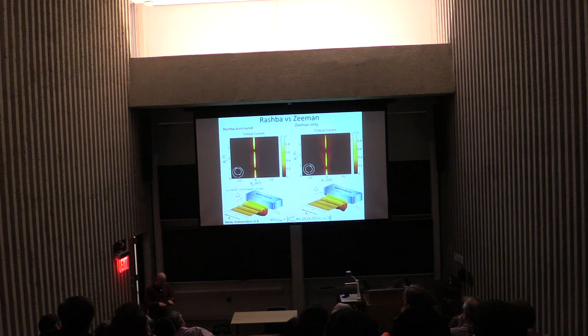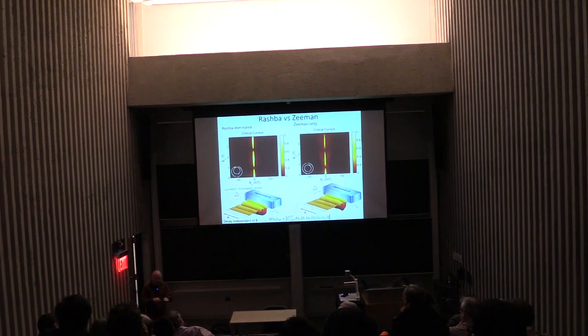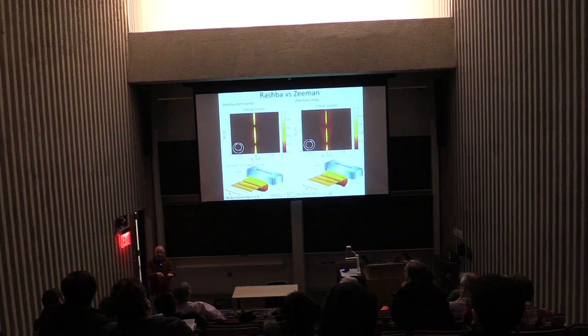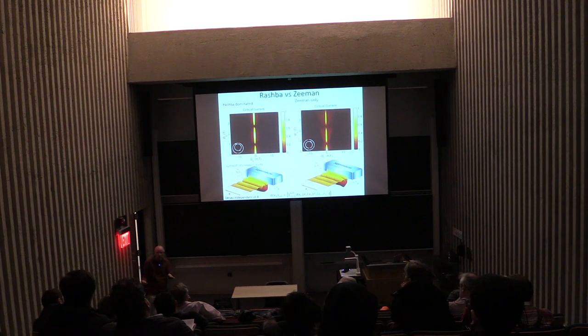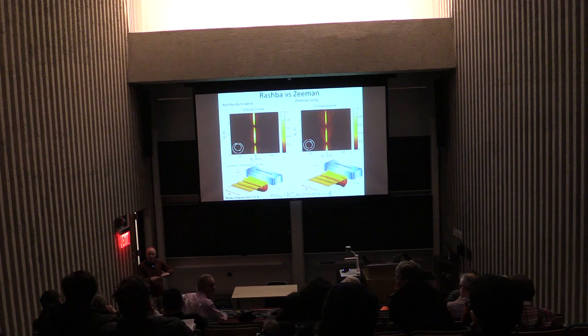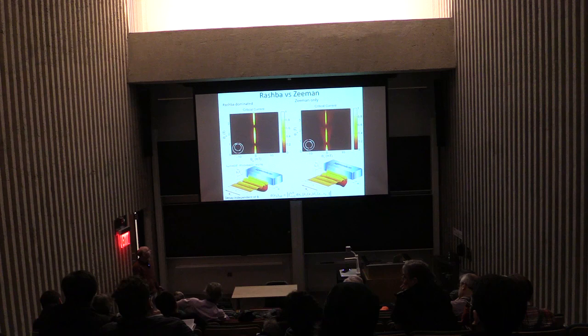What we believe has to do with something that's related to a Doppler effect. If the edges of your superconductors are a little bit rough, on the nanometer scale, not something that you're doing deliberately, but just your conventional lithography does that, and you put a magnetic field in this direction, then your magnetic field lines will go up and down, which means that they're giving you some random phases into the junction. As the magnetic field increases, the size of these random phases will increase and will scramble the interference. So we believe it has to do with that. If we could produce more perfect junctions, I think this will improve, but this is our hunch. But yes, with niobium contacts, we can in fact see 1, 2, 3 of these nodes consecutively, not only one.